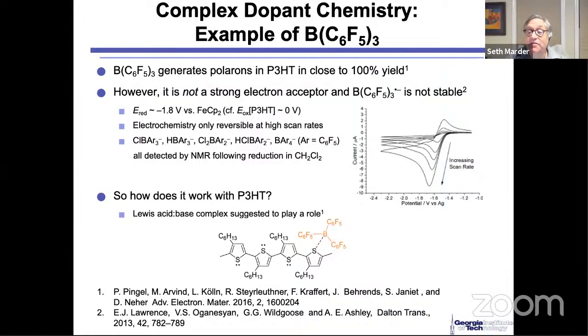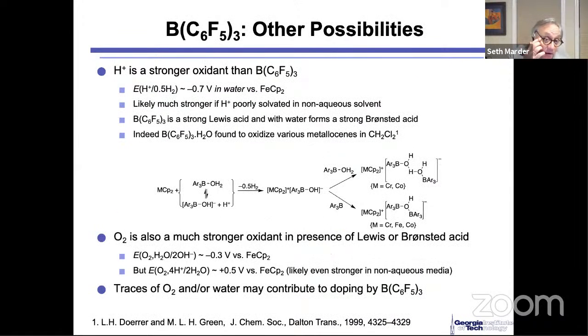The fact of the matter is that it decomposes. So this goes to the issue that you have no idea what your anion is. So then the question is, well, how does it work? And then some people suggested, well, you know, it basically dopes by coordinating to the sulfur, and that was sort of what happens. You know, the spectra are really not consistent with that, okay? So once again, I point out that it helps to know the literature.